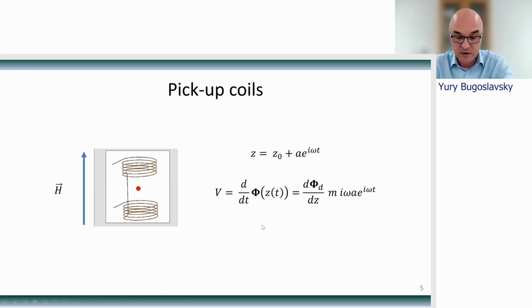Coils are commonly used to detect magnetic fields. The voltage generated at the terminals of a coil is proportional to the time derivative of the magnetic flux through the coil. Therefore, to make our magnetometer work, it is necessary to set the dipole vibrating, like shown in this little animation. When the sample comes close to the coil, the flux through the coil increases, and vice versa.